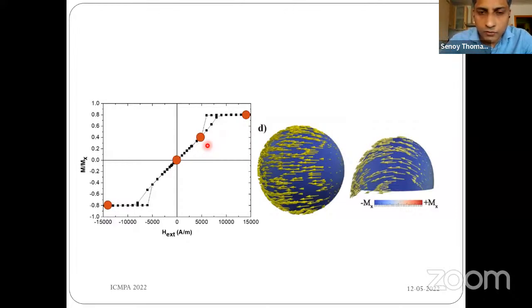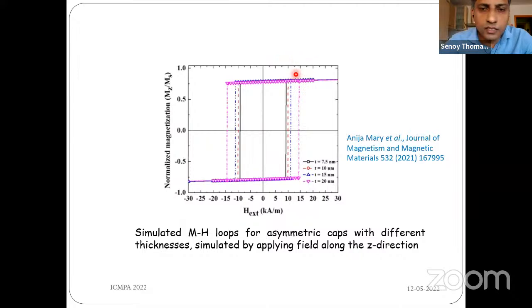And in order to investigate the shape anisotropy in the system, we applied field along the Z direction. And what we found is that the reversal is typical of a reversal via coherent rotation of the spins. So this basically tells about the shape anisotropy associated with the asymmetric system. Okay, so what we understand is that one could carefully tune the magnetization reversal process by just changing the asymmetry associated with the magnetic cap structures.